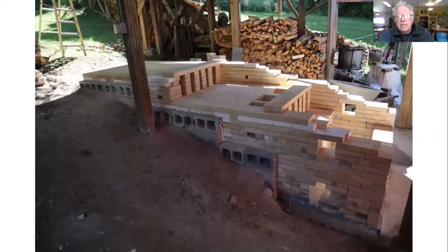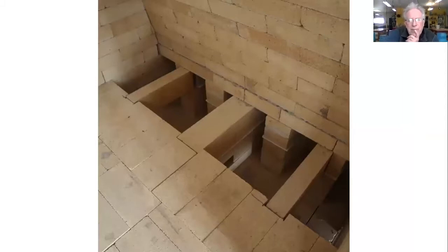But you can see the two layers of flues there, the openings that go into the kiln. So now in this photograph, we're up onto the last and final layer up there to the left, and that is going to be the salt kiln, a chamber in which we throw salt. There's that central wall that I was talking about. So normally in the original design, there were five grate bars, which are those long bricks there. And over the years, those grate bars had deteriorated a number of times. So I had replaced them a number of times. And at a certain point, I thought, well, you know what, I'm going to experiment and see if you really need a grate bar for this kiln.